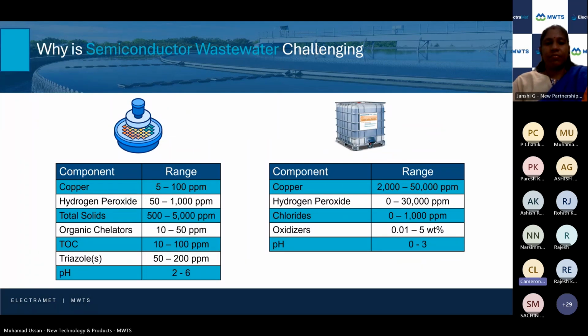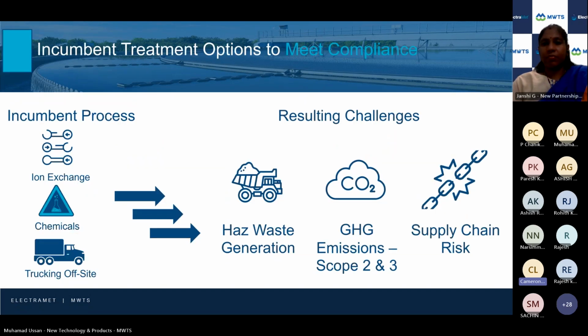And the reason why these waters are so difficult to treat is because there's a lot of stuff in there. If you have pretty clean water with one target constituent, it's pretty easy. For the CMP on the left here, the target is the copper. But you have a lot of hydrogen peroxide in there, solids, organics, and these all tend to negatively impact standard treatment solutions. On the right, you just have a significant amount of copper. That makes solutions like ion exchange chemicals very expensive to process it. So importantly, you have just large amounts of unknown chemicals. So this combination makes it challenging, right?